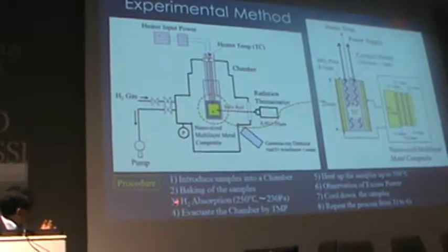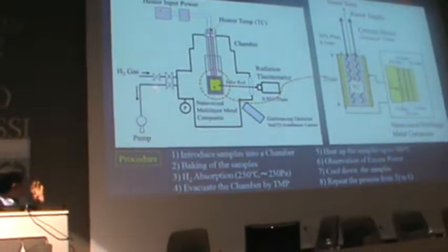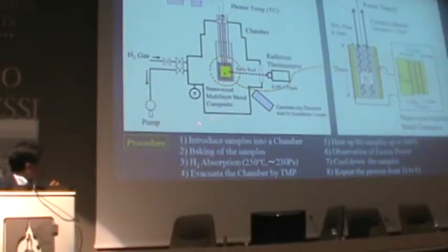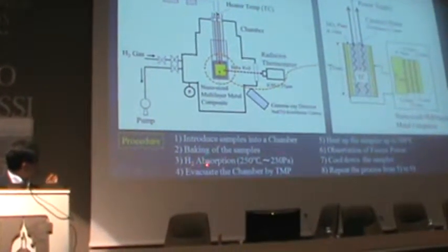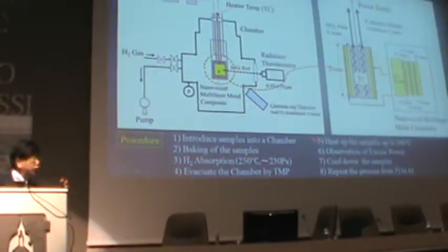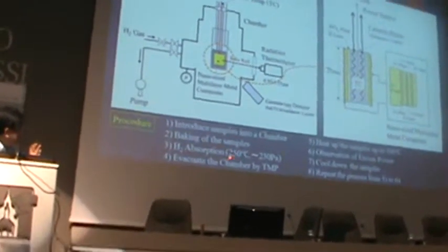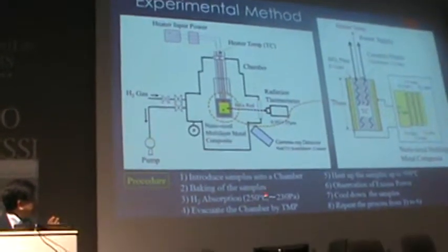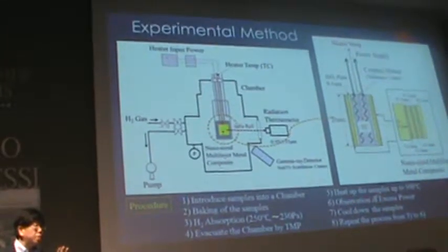And after that, we introduce hydrogen gas into the chamber. The temperature at the hydrogen gas introduction is about 250 degrees, and the pressure is 230 Pascal.